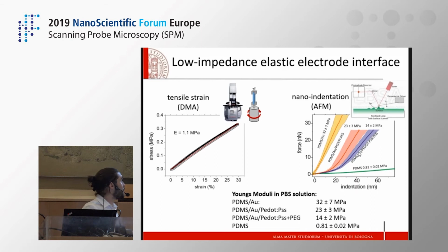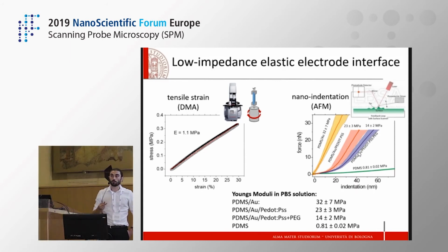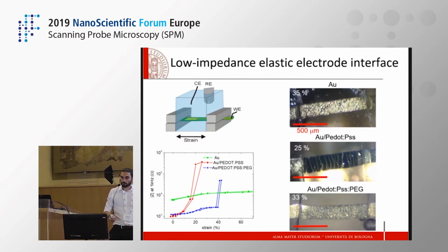And we see that with the gold addition, we have an increase of the Young modulus going to 32 megapascal, but once we add the polymer PEDOT:PSS, and in particular the polymer with the plasticizer, this Young modulus reduces to 14 megapascal, thus being more conformable and more mechanically compatible with the neural tissue.